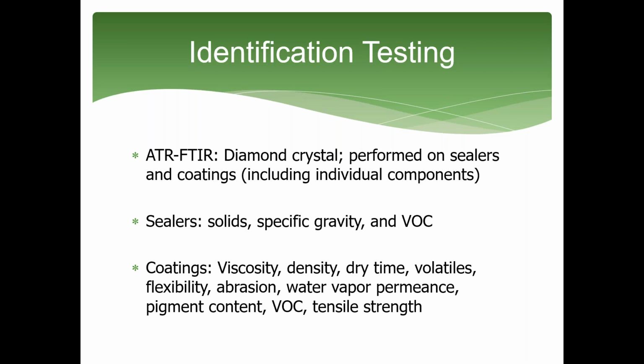Concrete sealers are additionally tested for solids, specific gravity, and VOC. Concrete coatings are tested for VOC and solids using the same methods as the sealers. However, they're also tested for viscosity, density, dry time, flexibility, abrasion, water vapor permeability, pigment content, and tensile strength.